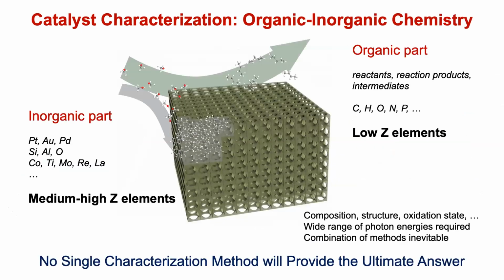What we forget, and that is another complication, is that catalysis is not always, organocatalysis is an exception, because there is carbon or whatever, but it's often an organic-inorganic chemistry thing. Also in homogeneous catalysis, you have a metal complex with ligands and an organic molecule. And it means that you often have a high Z with a low Z element. And there starts to be an issue, because techniques are not always amenable towards the low Z or the high Z. So you will have to make sure that you're able to measure both at the same time if you want to understand catalysis.